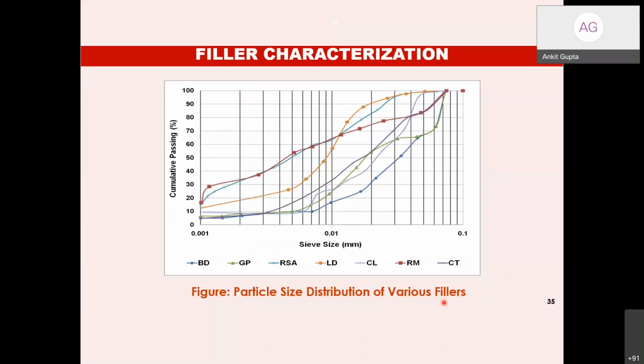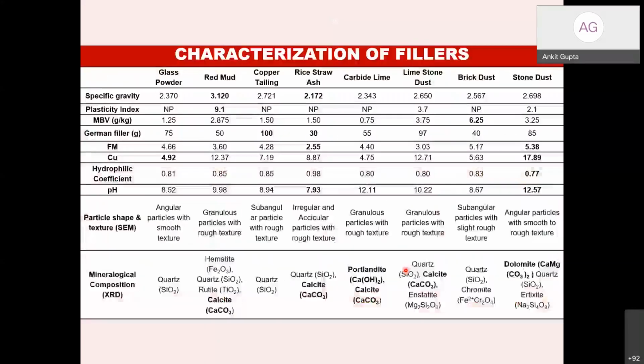Now coming to the first part, that is the characterization of the filler. Okay, so it has been shown in the previous literature that fillers having small size particles show some strong chemical interaction with the bitumen, and they normally have high stiffening power also. So you can see in this the limestone dust, the rice straw ash, and the red mud. These are one of the finest fillers because we have some values in this chart also. The fineness modulus is the smallest, and the D50 values are also small.